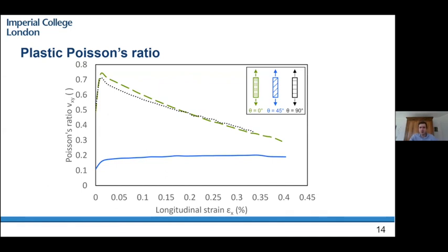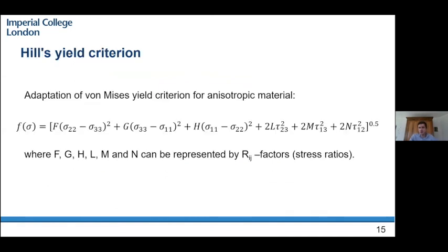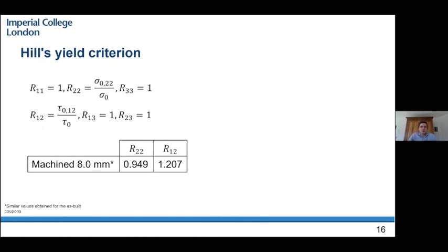Another important part for the plastic analysis is material yielding. For isotropic materials, the von Mises yield criterion is often used, but this one is no longer valid for anisotropic materials, where the Hill's yield criterion can be utilized. Hill's yield criterion essentially adapts the von Mises yield criterion with Rij factors, which fit it to the anisotropic material behavior. These Rij factors can be determined using stress ratios, and you can see the results below for the